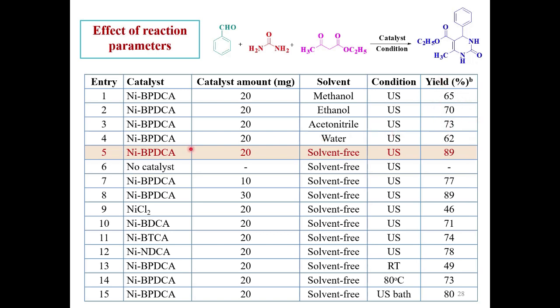Again, when we compare this NiBPDCA with other catalysts, if no catalyst is used, the reaction cannot proceed. Again, we have tried 10 milligram and 30 milligram of nickel BPDCA. We increased the amount of the catalyst, and we observe that at 10 milligram, 77% is observed, while at 30 milligram loading of nickel BPDCA, 89% is observed, and therefore we concluded that 20 milligram is sufficient to enhance the percent yield of the product. And again, when we compare with other organic linkers, the percentage yield is much less as compared to BPDCA.